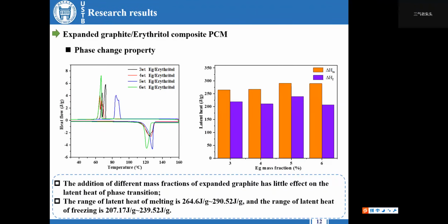For phase-changing materials, the phase-change characteristics are worth studying. It can be seen that with the addition of different mass fractions of expanded graphite, the latent heat of phase transition of erythritol doesn't change much. The range of latent heat of melting is 264.6 to 290.52, and the range of latent heat of freezing is 207.17 to 239.52. It shows that the as-prepared composite phase-changing material exhibits excellent phase change properties.